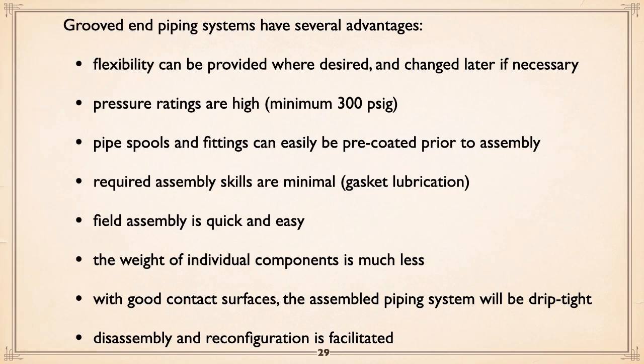Now, I like grooved end systems. Why? Flexibility can be provided where desired and changed later. In other words, you can use the rigid couplings all over the place, except where you want flexibility, you can go to the conventional coupling, which allows this 1/4 inch of movement. The pressure ratings are high, minimum 300 psi, and you can get well beyond that. Coating pipe spools and fittings is an easy pre-coat because the headers or whatever can all be disassembled into a collection of easy to coat pieces. Assembly skills are minimal. You got to remember to lubricate the gasket. The rubber part has to be lubricated so it can slip, and that's about it. So field assembly is quick and easy. The weight of components is less. With good contact surfaces, the assembled piping system will be drip tight, and disassembly and reconfiguration is facilitated. It's easy to do.